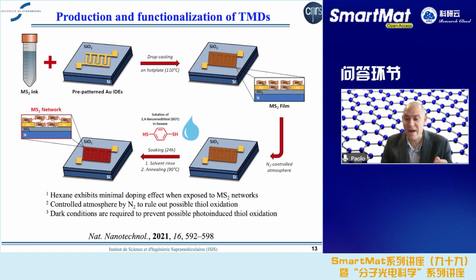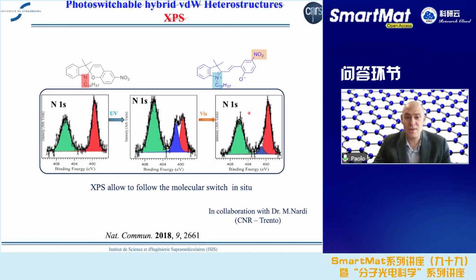at room temperature. Spiro, actually, if you want to play with dipoles, is better, because the spiro is neutral and the mero is zwitterionic, so the change in dipole moment is extremely high between spiro and mero. Whereas with azobenzene, I don't think you can reach such a large change in dipole moment. So if you want to play with change in dipole moment as a way to dope your 2D materials, then I would remain with spiro. Also, spiros are easy to synthesize, so this is doable. Azobenzenes, of course, are much more available commercially.